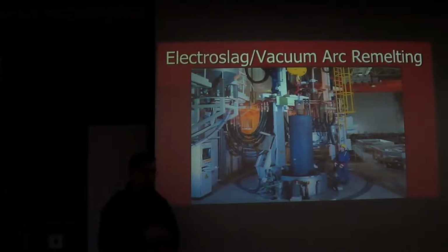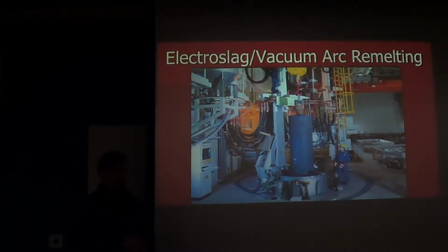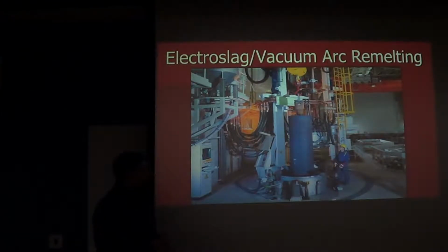So this gives you a very clean steel, but because of the way in which you're remelting it, going from the bottom to the top, and doing it very slowly, and just a little bit at a time, you're able to get a much more uniform composition. So we use this process. Most of the time it's driven by the desire for very clean material, but it does give us the added benefit of having very reduced segregation. So we could use it for that reason in certain situations.